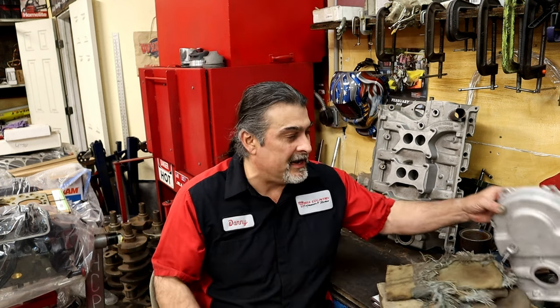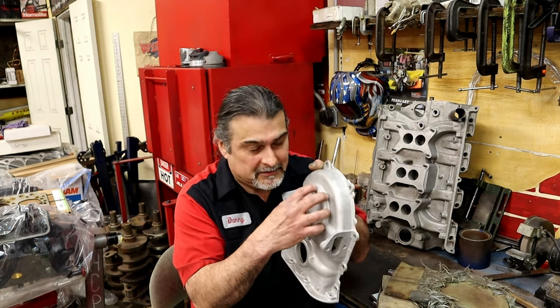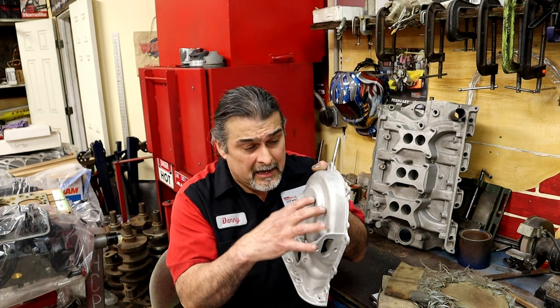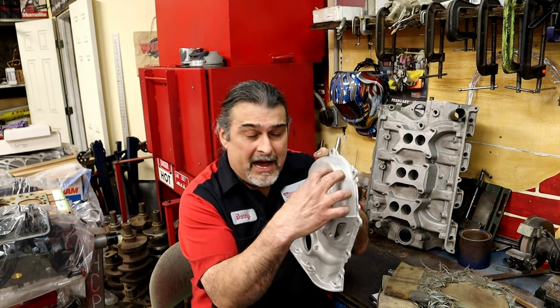If I sit there and get medieval on it right here, anywhere, it's going to distort. It's going to get hotter here than anywhere else, and you're going to have a bent up piece, all distorted. I can weld an aluminum cylinder head and mill it, and it'll mill in 1 or 2 thousandths. How can I do that when the head doesn't even distort that bad? It goes in an oven, gets preheated, crank it up. I'll heat it up till the seats almost fall out. So 300 degrees, you're doing good. You're preheating the complete head.